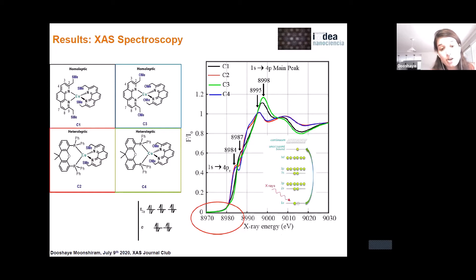We can determine the coordination geometry of all complexes simply by looking at the XANES spectra. All complexes show a distinct shoulder between 8984–8987 eV, corresponding to the 1s→4pz transition where the 4pz is localized on copper in a tetragonal or square planar geometry. We don't see any pre-edge features — pre-edge features would consist of 1s→3d transitions, which are formally dipole-forbidden but gain intensity from 3d-4p mixing. Since copper(I) is a 3d¹⁰ system with no vacancy in the d levels, we observe a lack of a pre-edge feature. The XANES spectra of all four complexes show small changes in the rising edge features, indicating small variations in local coordination geometry and local symmetry, corroborated by X-ray diffraction.